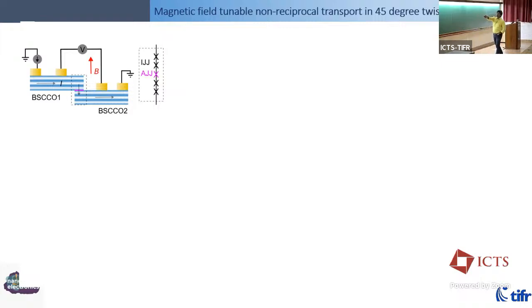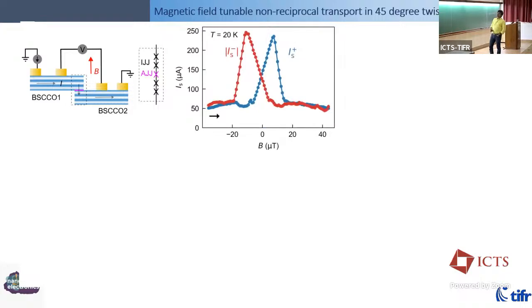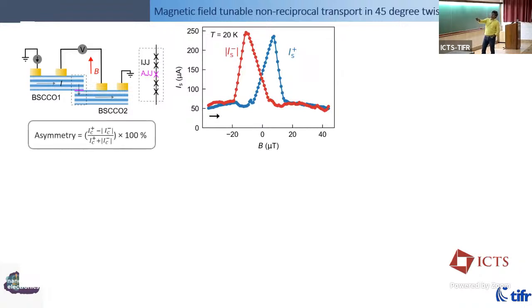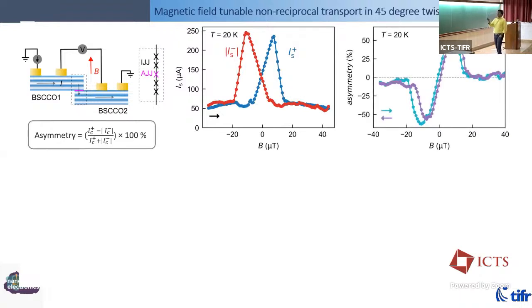So this is the Josephson junction, the purple colored artificial Josephson junction, and you have these intrinsic Josephson junctions, and we can measure these by applying a perpendicular magnetic field. Okay, and what we see is that asymmetry in these, which is characterized by this parameter, is tunable with magnetic field, but it's actually tunable with a very small magnetic field. Earth's magnetic field is in this range somewhere.